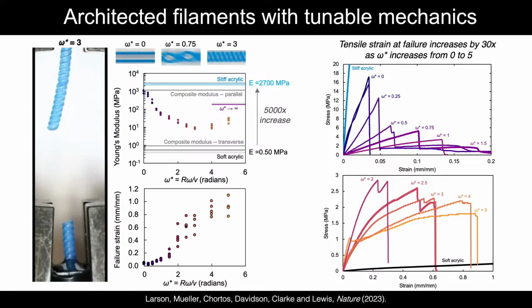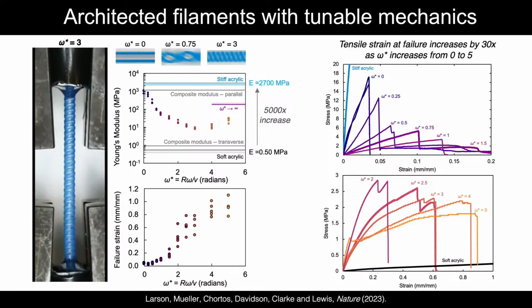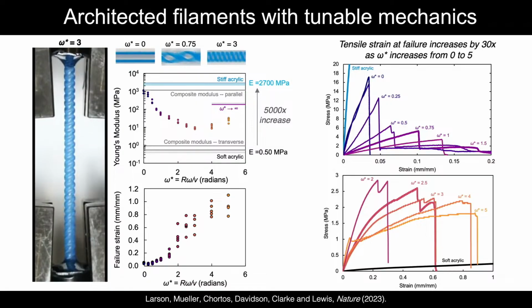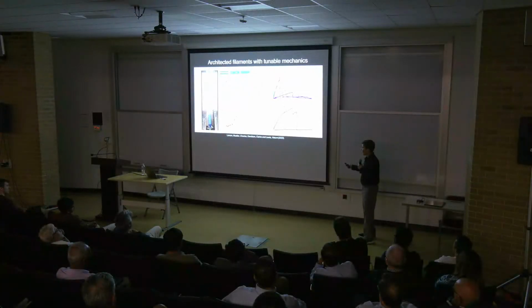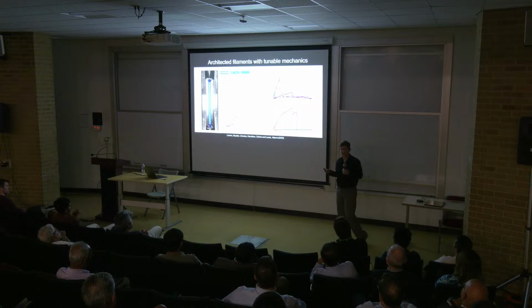But here you can see that the failure strains are also highly tunable because essentially as we go from something that's stiff and brittle that has a very low strain to failure, to something that's highly soft, where now as we increase the rotation rate and become ever more dominated by the soft phase as we're layering that, then we get strains out to almost 100% of the initial fiber length. So by simply changing the rotation rate of these two materials as we're integrating, something very simple, right? But nature does this all the time.